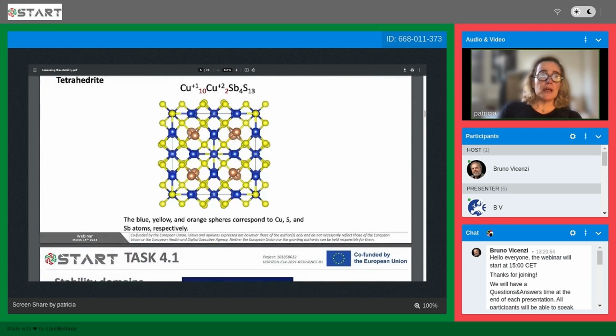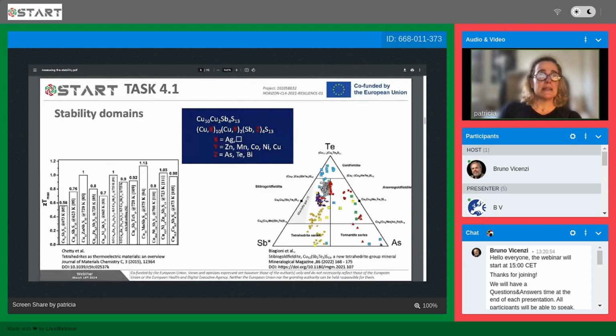What we tried to do when we started was to see how we could maximize the performance of the thermoelectric materials. If we go to the literature, we see a lot of different elements tested, and we decided, okay, let's see what we can get with these elements too. Of course, for the antimony, we don't really want to replace it with arsenic or tellurium, which are not very nice, and tellurium is not very abundant. So we stick with antimony.